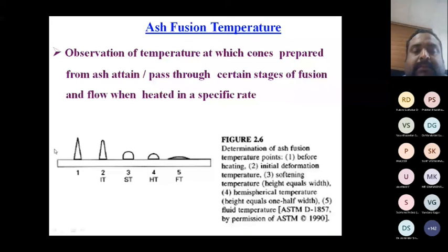Secondly, when the ash cone slumps and the height of the cone is equal to the width of the base, that is called softening temperature. Then when the height becomes half of the width, it is called hemispherical temperature. The last one is flow temperature, fluid temperature. These are four different stages of ash fusion temperature: initial deformation temperature, when the tip melts, then softening temperature, hemispherical temperature, and flow temperature.